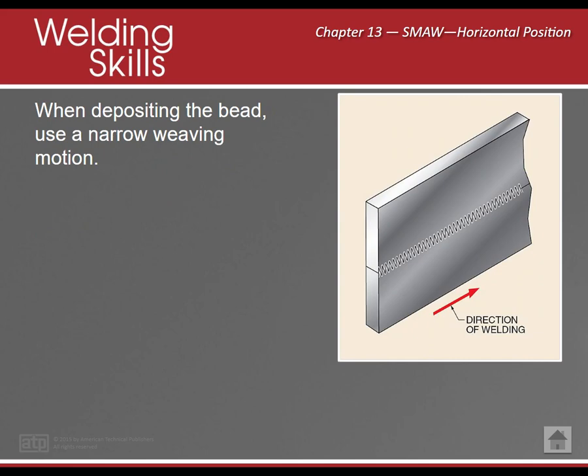When depositing the bead, you can use a narrow weaving motion, so that would be like up to down. One of the downfalls of doing this as a beginning student is number one, going too wide with that weld bead. Remember, 5/16 to 3/8 of an inch is as wide as you want that weld to be. So sometimes students will go above that or wider than that and have too big of a bead. Another downfall of the weaving is students will spend too much time weaving in one spot, and what happens is they get too much weld in that area, and then you have your weld puddle that starts to sag. So you can weave, but you have to do specific things in order to do it correctly. So as a beginner, I don't recommend doing a weaving motion until you get a little bit more experienced with horizontal welding.